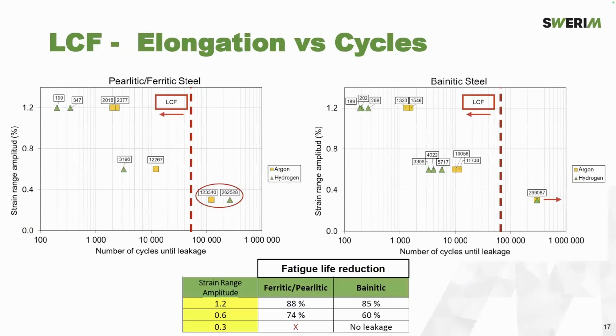So if we go to low cycle fatigue, we performed different tests at 1.2, 0.6, and 0.3 strain range amplitude. And we can see that there is a quite detrimental effect in hydrogen environment, with a reduction of 88% and 85% at this strain level, and 74 and 60% at 0.6. And we saw that at 0.3% strain range amplitude for the ferritic steel, we see a really high number of cycles, which can be considered as not low cycle fatigue anymore. And here we didn't show any leakage in the bainitic steel.